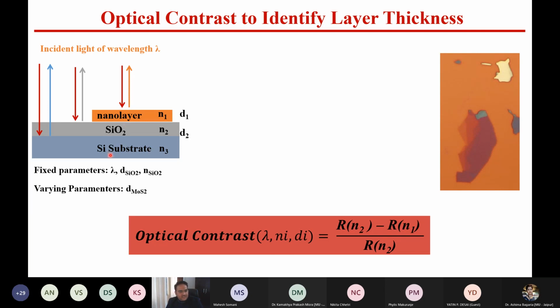So what you see here is a silicon substrate with a dielectric constant, say N3. Then you have a silicon dioxide, which is N2, and then you have a nano layer of, let's say, MoS2 or WS2 or any kind of material which you want. But the important aspect here is that the dielectric constant is a function of lambda. The incident light is very important here. So you can see the picture here on the right hand side.